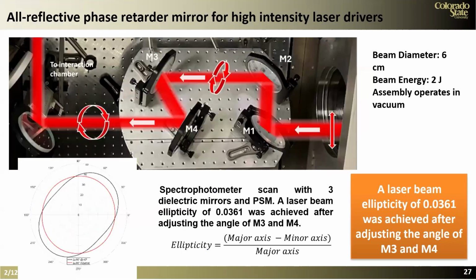We're also playing some other games with the Aleph laser. What I show here is work that we did recently. One of the challenges with high intensity lasers is that you cannot use regular optical elements. The way to make a circularly polarized beam out of a linearly polarized beam is to use a wave plate, but wave plates are not good for propagation. In this case, we are propagating joule level pulses of about 40 femtosecond duration.